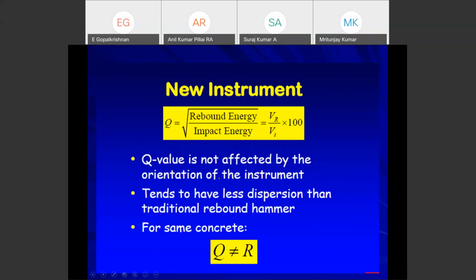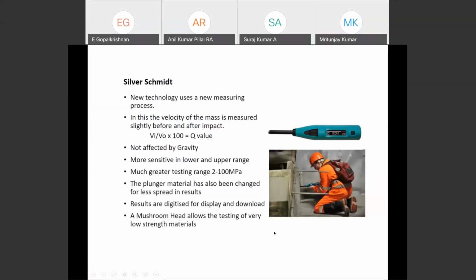We heard about the new generation hammers, because everybody is familiar with it since it's a basic test. There is the Silver Schmidt, which is the latest development, which gives the Q value. There is a difference from the R value, which you used to get in the conventional instrument. For the same concrete, the Q value is not equal to the R value. What is the difference? The new technology measures the Q value. For the Q value we measure the rebound velocity optically, whereas we measure the rebound distance mechanically in the R value.